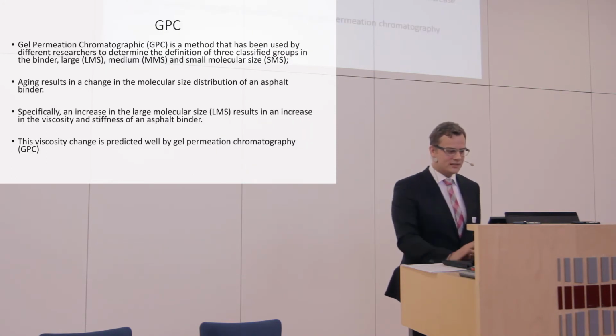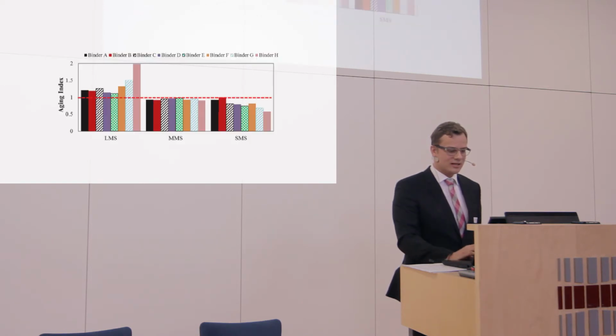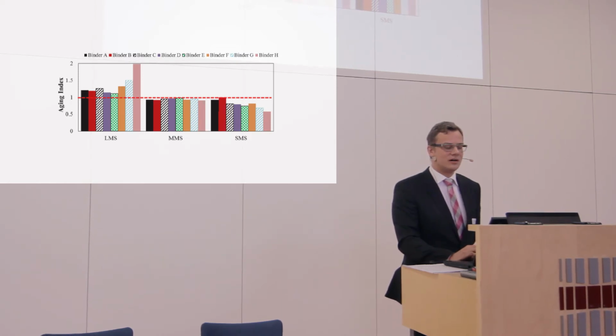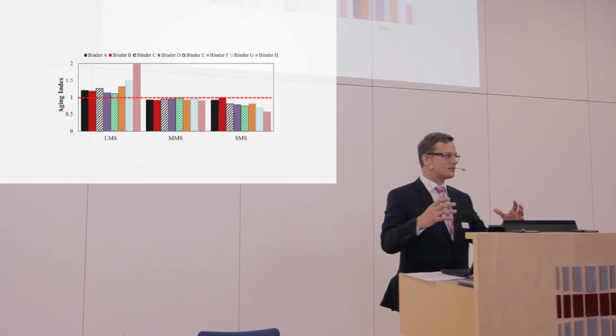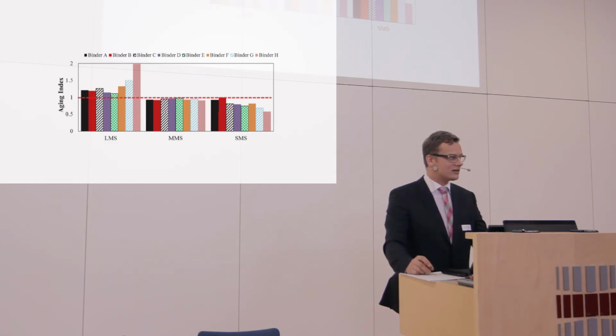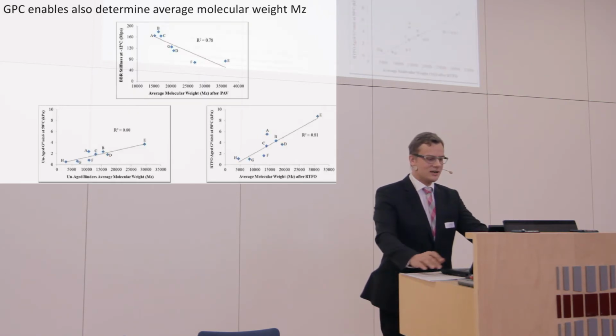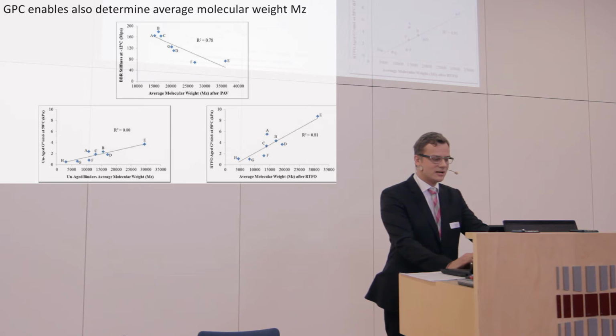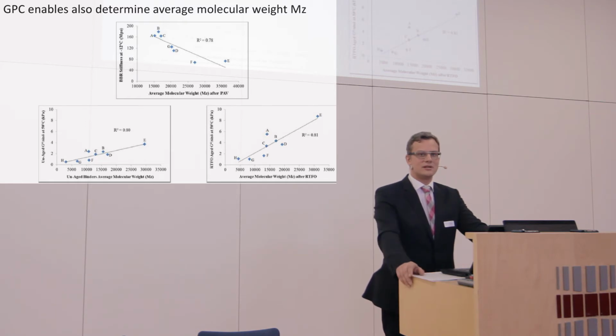Then we made a gel permeation chromatography study. It shows how fast or how severe the aging is, how different sizes of molecules change places, and GPC also enables us to determine average molecular weight. So we could find quite good correlations between average molecular weight and low and high temperature grades.